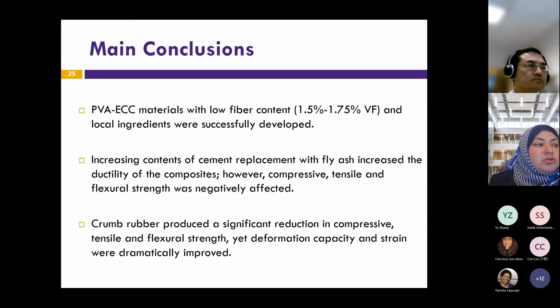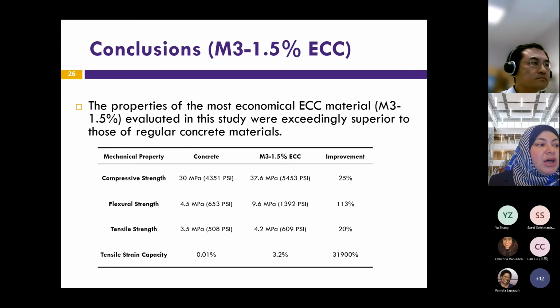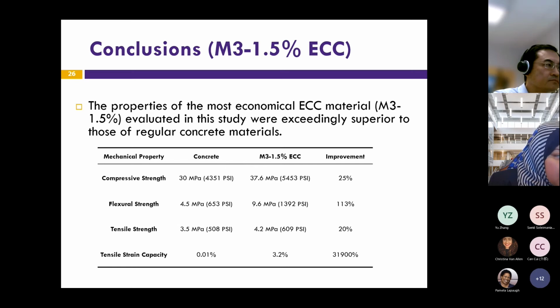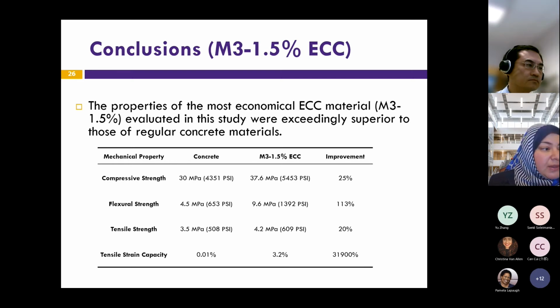This slide here shows the best mix that we were able to develop in terms of economics and performance. We call it M3 1.5%. And you can see here the properties of it. It had a compressive strength 25% better than regular concrete, flexural strength 113% better than regular concrete, a tensile strength of 20% better than regular concrete, tensile strain capacity of more than 31,000% better than concrete. We actually use this mix in an accelerated loaded testing study that is currently going on in Louisiana.